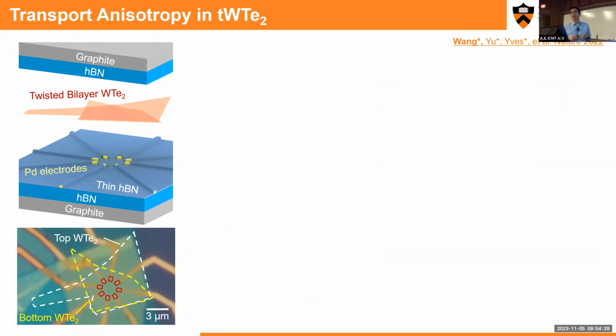This measurement was possible with this kind of design, where we only touch the bulk of the twist area. The reason is that this monolayer tungsten ditelluride is edge conducting, and the typical method is going to touch the edge, and the monolayer area is also going to confuse your measurement. So in all our measurements, we only touch the twist area as a contact, and then we can measure either the anisotropy or transport property of the material.